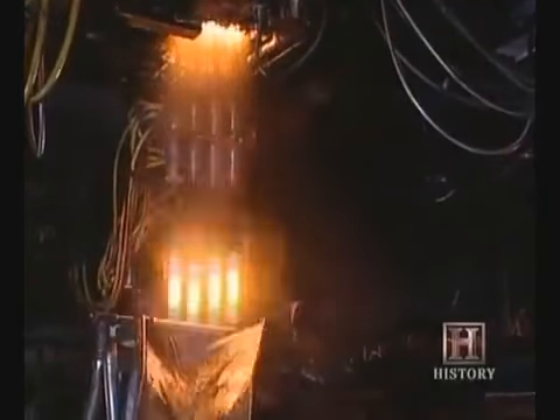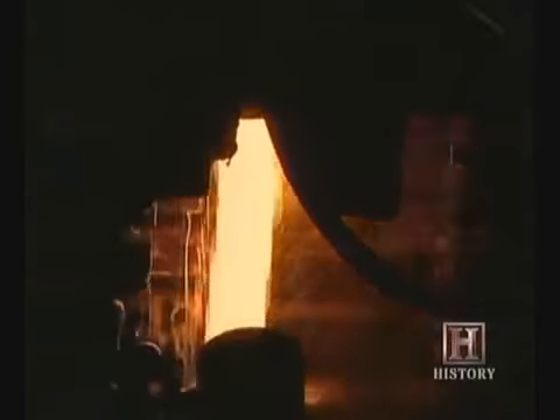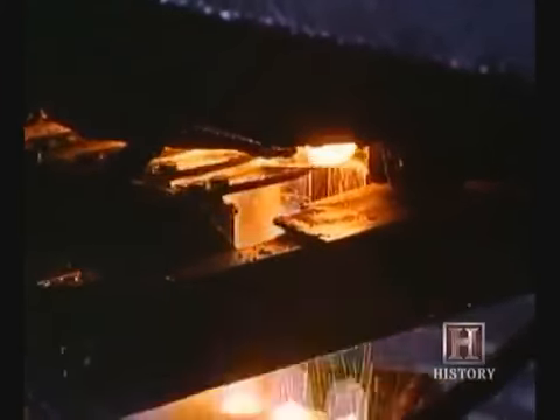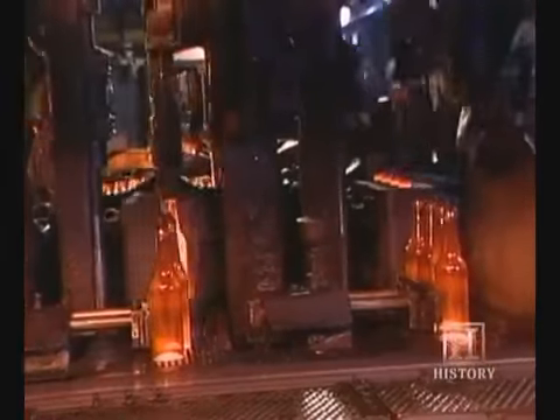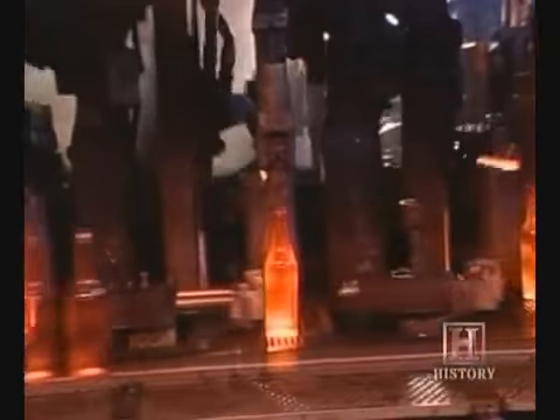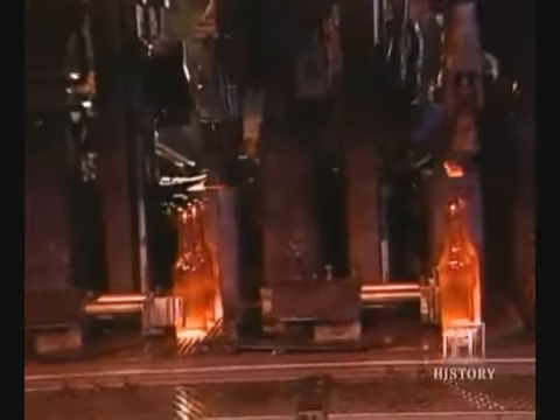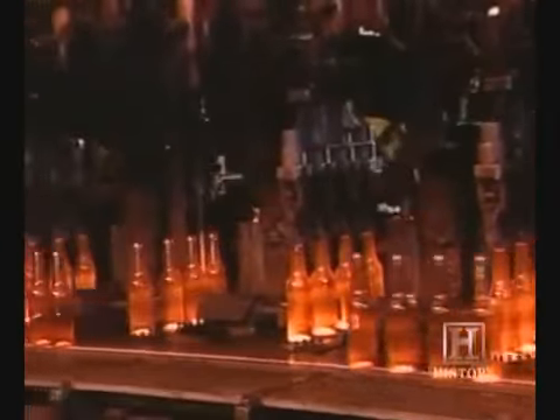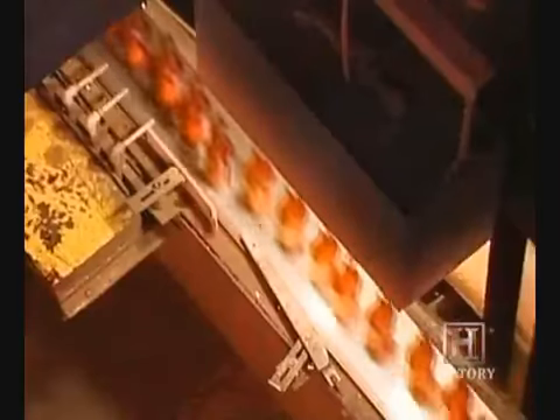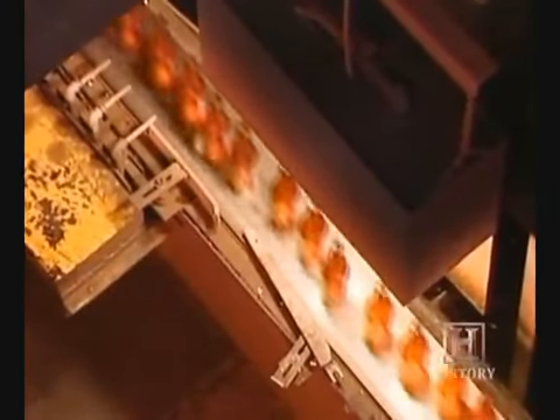After the glass is melted in the furnace, it's delivered to the forming machine. The molten glass gets sheared into uniform pieces called gobs, and then blown into the mold shape with compressed air. The glass enters the forming machine at 2,100 degrees Fahrenheit. Formed glass containers leave the machine at 900 degrees Fahrenheit in less than 10 seconds. This rapid cooling helps the glass retain its shape.